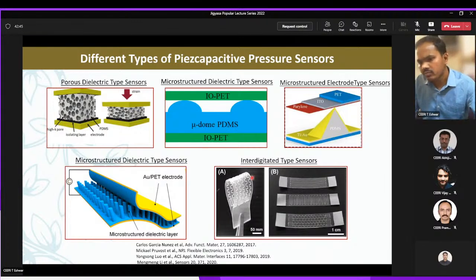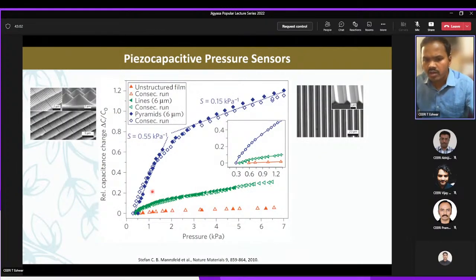Also, other kinds of pressure sensors are there, like interdigitated, rather than these, which are all parallel plate capacitive. So here, these are interdigitated type capacitive pressure sensors. Now with this capacitance pressure sensor, people were able to develop pressure sensors with a sensitivity of almost 0.55 kilopascal inverse, up to about 2 kilopascals.